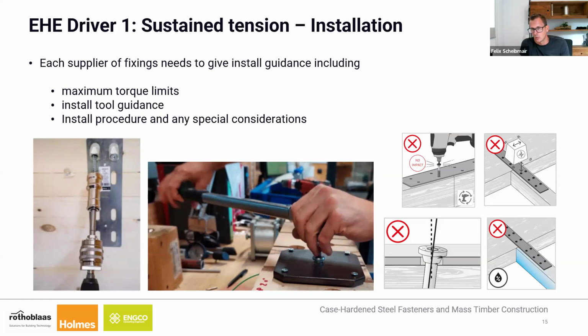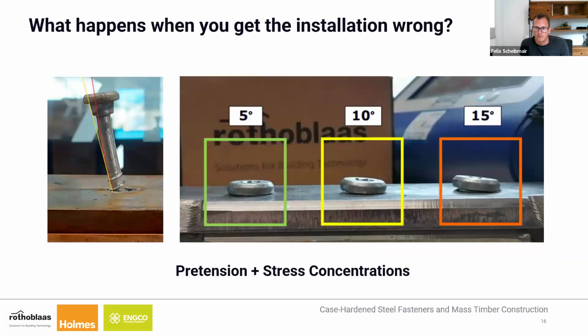So it's quite critical that these are followed. And if we skip to the next slide now, Eric, there's some very good reasons behind that. So if we look first on the right-hand side there, that gives a little bit of an indication of a deviation in terms of angle when you're installing a screw into a steel plate. You can see that it becomes quite noticeable from 10 degrees.